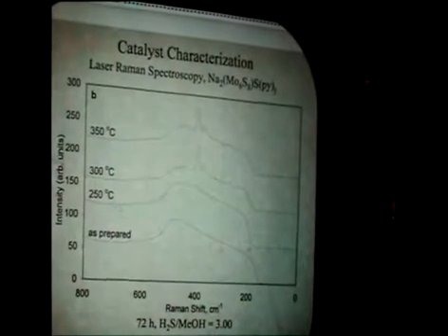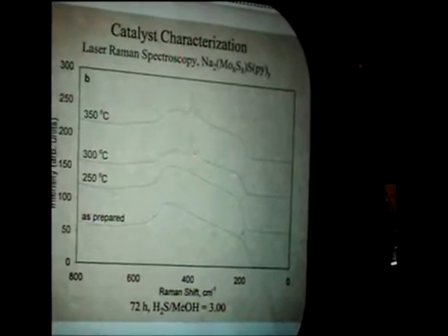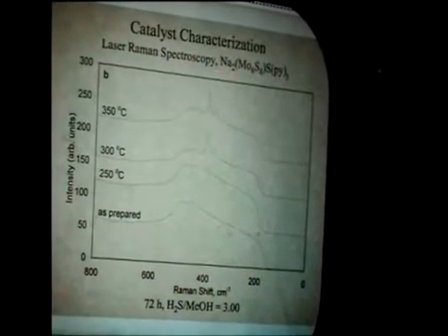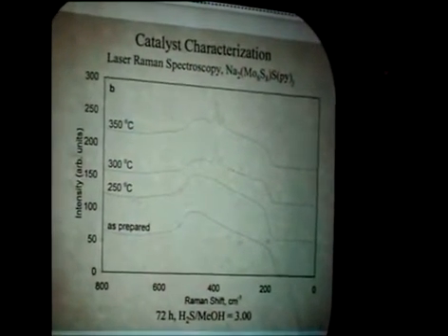By laser Raman spectroscopy, again, we showed the sodium material, and you can see a little bit of MoS2 at 250, but it becomes very apparent at higher temperatures that the sodium material tends to convert somewhat to MoS2. I should point out that laser Raman spectroscopy is very sensitive, so it's not full conversion to MoS2, but it's pretty clear that that's what's happening.